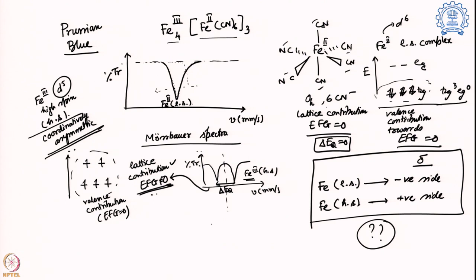So what I expect, this band will come something like that over here. And this will be the iron 3 high spin system. That is what we are going to expect for this full system. Again, iron 2 is low spin, no contribution from the lattice or valence, so single line. Iron plus 3 outside, high spin system, coordinatively asymmetric, there is a delta EQ value. But the question is, why is the delta value of iron plus 2 low spin shifted toward the more negative side compared to the iron 3 high spin? That will be covered a little bit later, but this is what we are going to see.